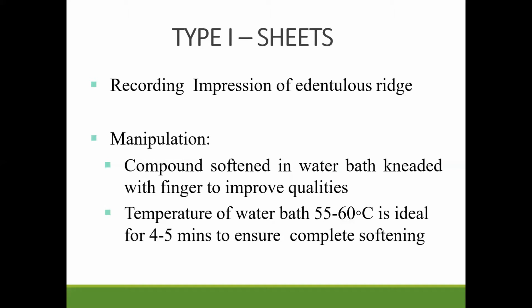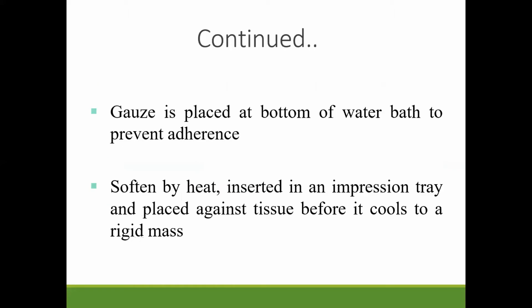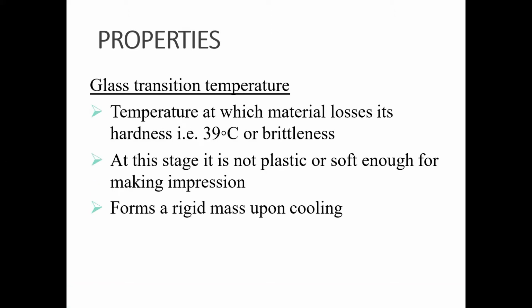So basically manipulation, how it works is we soften the impression compound in a water bath at a temperature of 55 to 60 degrees Celsius, for around 4 to 5 minutes so that it is fully softened. Now, after it is softened, a gauze piece is placed at the bottom of the water bath to prevent the adherence of impression compound with the rubber ball. It is softened by heat, inserted in an impression tray and placed against tissue before it cools to a rigid mass. The properties include the glass transition temperature, which is around 39 degrees Celsius.